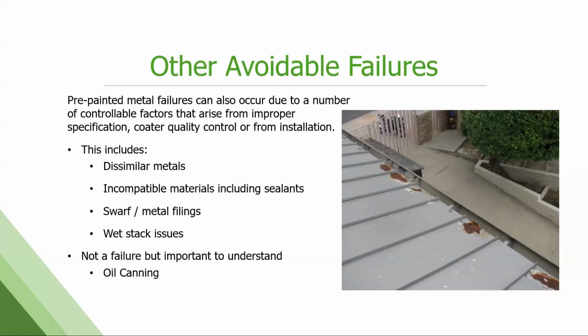Other failures that we need to avoid, this is using other materials and metals. So dissimilar metals or galvanic corrosion. There's whole hour-long presentations on that we could get into. You've got to be really careful in corrosive environments around the marine locations, salt water, not mixing wrong metals together, or you'll get this kind of a corrosion occurring. This is stainless steel fasteners with a painted galvalume substrate. You have galvanic corrosion, this is about 300 feet off the surf break outside of San Diego, so a highly corrosive environment. The galvalume panel is sacrificing itself to protect the stainless steel fasteners. That's what's happening there.